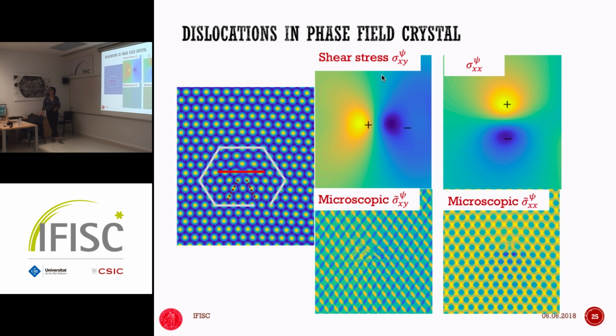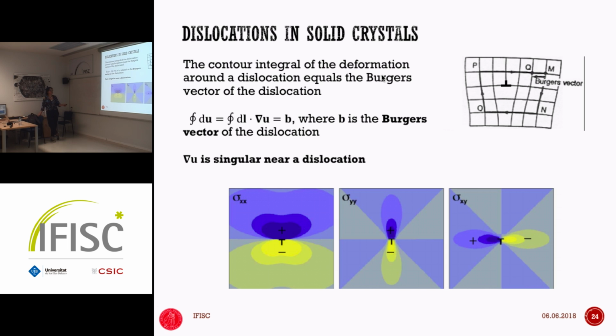Luiza, yeah. U was the added deformation. It's something that you were adding on, while here it seems it's something that you are measuring when you have the defect spread. That's true. In order to derive the stress, we used an affine transformation imposed from outside, but here it's an internally induced one. But the stress can still be applied. You can still have the same definition of the stress. This deformation field doesn't need to be imposed by an external field. It just comes because you have a dislocation. That's why dislocations localize deformation. So even if there was no deformation there, if you have a defect, it will produce deformation, but it's also localized.